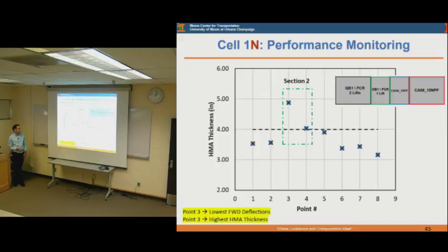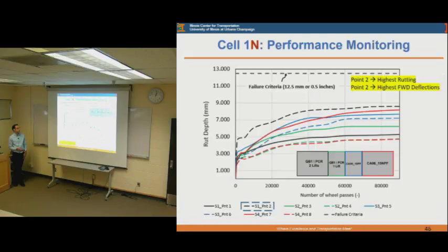So point 3 here had the highest HMA thickness and also had the lowest FWD deflection. So there are still trends that apply. And I'm showing here just the variation between the different points in each test section, which were averaged before, and how they vary. So again, in some sections, the variation is quite bigger. But if you look at the scale, they all were between 4.5 millimeters and almost 7.5 millimeters.